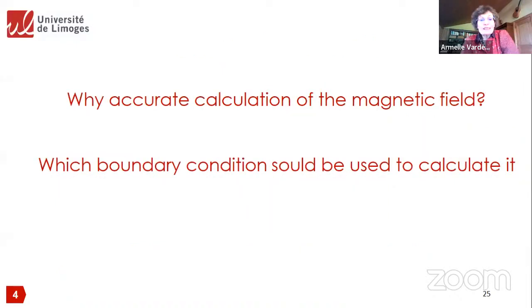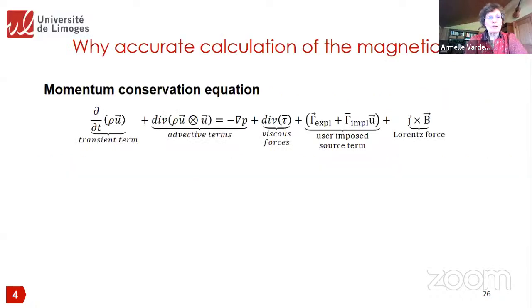Okay. Why is it important to have an accurate calculation of the magnetic field, and which boundary conditions should we use to calculate it? If you look at the momentum conservation equation, sorry for this equation, even if you don't know it, there is no problem. Just look at the source term which appears in this equation. This source term depends on the magnetic field and the electric current density. So if one of them is wrong, for sure, the velocity of the gas could be wrong.